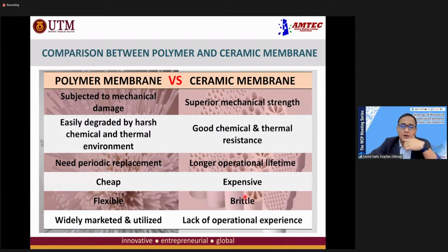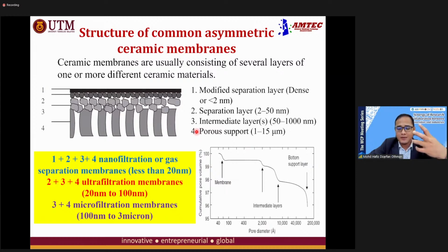And the common structure of ceramic membrane is what we call asymmetric, meaning that the top and the bottom layer don't have the same structure. The bottom layer normally is porous. So we have to do some deposition technique in order to deposit another layer and further reduce the pore size. The smaller the pore size that we need, the more deposition layers we have to do on the porous support.